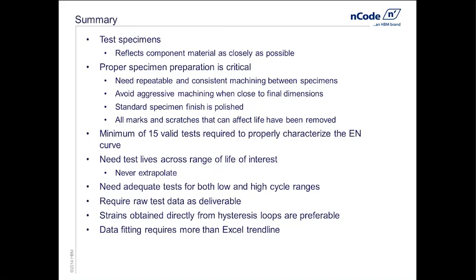A simple regression using a trend line inside of Excel reverses the independent and dependent variables. The independent variable is the y-axis in our test, whereas in a standard regression it's the x. So the regression is a little more complex than just doing a simple Excel calculation using a trend line.